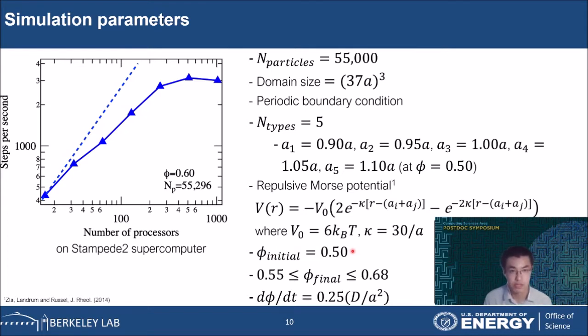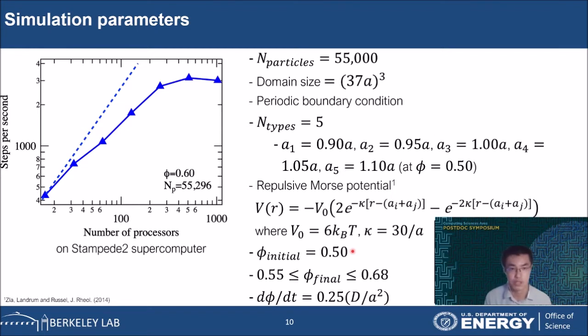There are five types of particles. Each has a slightly different radius and each type has 11,000 particles. This size polydispersity is used to suppress crystallization. A steep Morse potential cuts off its attractive part to model a nearly hard sphere system. We vary final volume fractions to span from a dense liquid to dip into the glass. We also impose a fast quench rate — D over a-squared, which is the inverse of the particle diffusive time describing the time for a single particle to diffuse its radius. This rate guarantees that all quenches will finish within a fraction of the diffusive time.